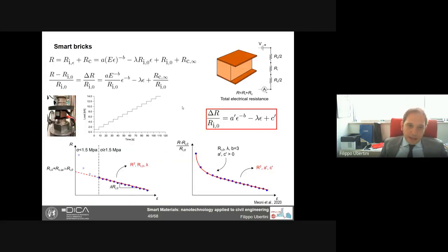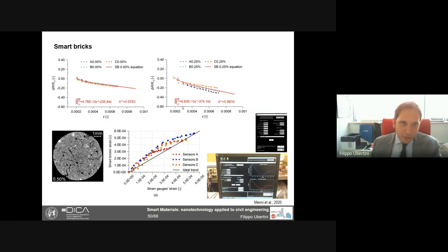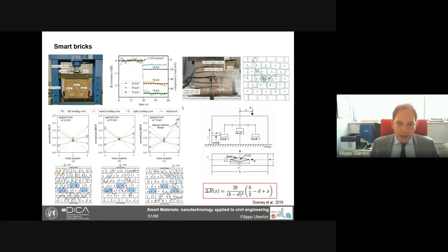And this model shows that from the experiments, we can say that below 1.5 megapascal of compression, the sensing capability of the sensor is governed by the contact, while above 1.5 megapascal, it's governed by the internal piezoresistivity. And by the way, this model fits very well the experimental results and shows very consistent strain measurements with respect to what we measure with strain gauges. So coming to some structural applications, here you see one first application of a small wall under in-plane loading with 3 bricks. What we did here was increasing the load until provoking some damage.